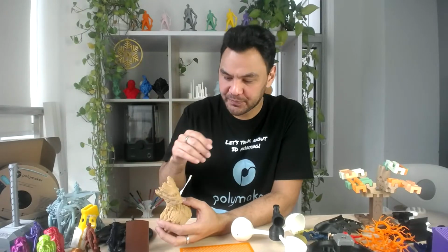From the history, from the background, PolyWood was created because the wood mimic filament on the market has wood powder inside. What's the problem with wood powder is that it would clog the nozzle. If you have an accumulation of this wood powder, then it will just clog the nozzle. So we wanted a way to create a wood mimic filament that doesn't have any clogging problem. Well, what's the best way to solve the clogging problem? You remove any wood powder. So we remove all the wood powder.